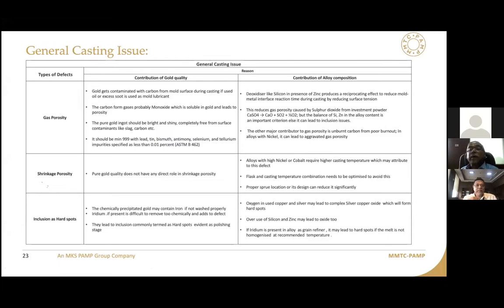Now, how the alloy contributes to gas porosity. If you are not using a proper balance of silicon and zinc, then at the interface you will have gas liberation. The calcium sulfate from the interface will get degraded and will produce sulfur dioxide gas that will lead to sulfur dioxide related porosity. So the proper silicon zinc balance is very important. And of course, if carbon is there from your investment powder, it will definitely lead to gas porosity.